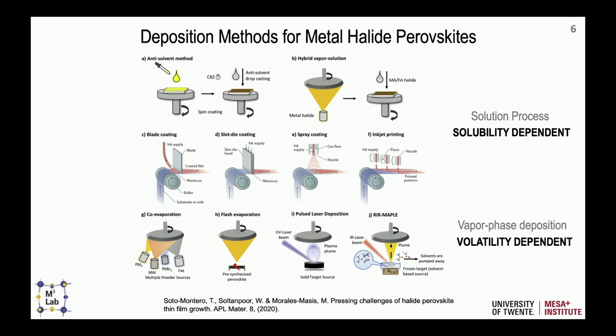Now we go to the case of vapor phase deposition, where we already heard about co-evaporation, and you saw from the presentation earlier that when you do co-evaporation, you have different boats for each of the precursor salts. And that's because each of these precursors for the perovskite has a different volatility. So what you do is you heat up, you use only thermal processes, and by heating up these ones independently, you can control the stoichiometry of the material. But once you have a very complex composition, you need a separate boat for each.